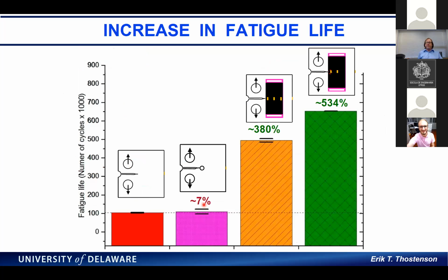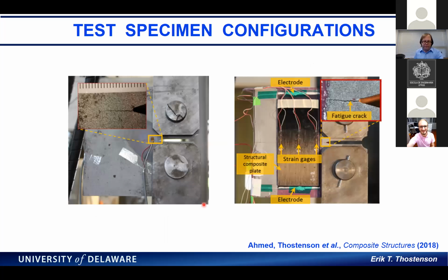And so these are the results of fatigue life. This isn't showing any sensing results, but it shows that the repair can be very effective. The crack stop hole didn't really increase the fatigue life that much, whereas when we applied the composite without a crack stop hole, we got a 380% increase in fatigue life. That's quite significant. When we also drilled a crack stop hole, we saw an even higher, over 500% increase in fatigue life. There are some practical implications, as this was difficult to do because we would have adhesive flowing into the crack stop hole.